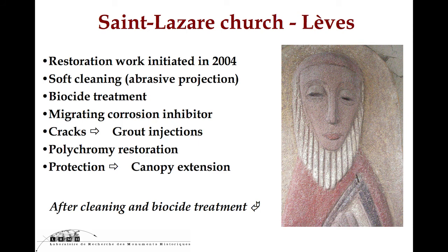So here, the restoration protocol. The restoration work was initiated in 2004. There was firstly a soft cleaning with abrasive projection, then a biocide treatment, and a migrating corrosion inhibitor applied. For the cracks, there were grout injections. Then there was the polychromy restoration. And for the protection, there was an installation of a canopy extension.